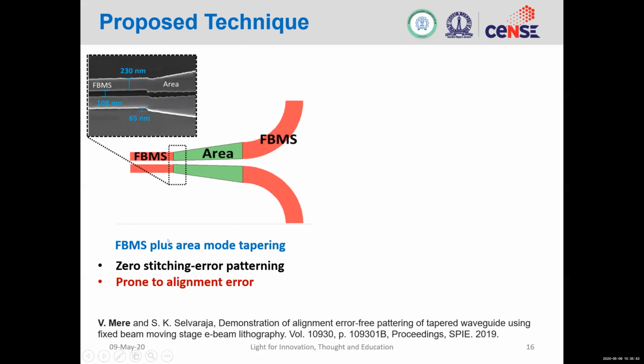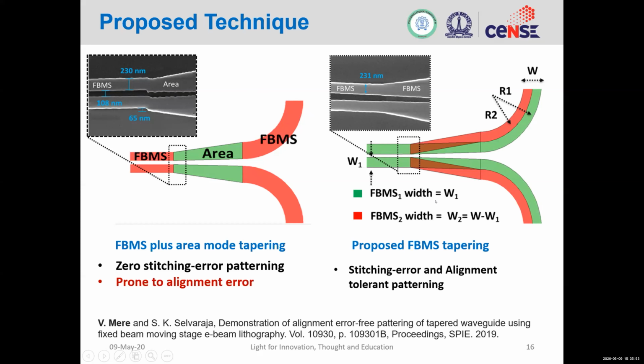So we have come up with a technique, which is the FBMS tapering technique. In this way, all the circuit is written using only FBMS. The larger widths are written by combining multiple FBMS paths, and as you come closer, you fix both the paths to a common point. In the process, you form a tapered-like structure. Here is an actual SEM image, which shows that this kind of discontinuity on the left-hand side is completely eliminated. In this way, you can achieve very smooth and alignment-error-free patterning using FBMS only.